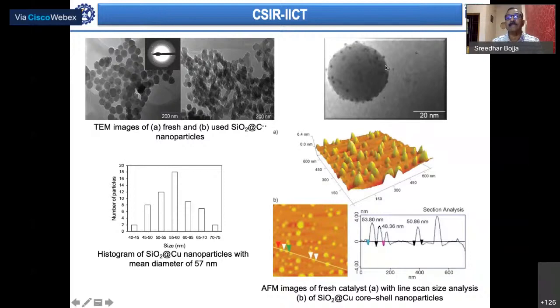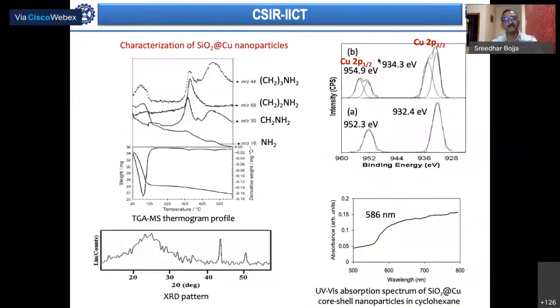This is one example: you have the silica particle on which copper nanoparticles sit on the shell material, and these copper nanoparticles are about 2 nanometers in size. So this is about silica copper.